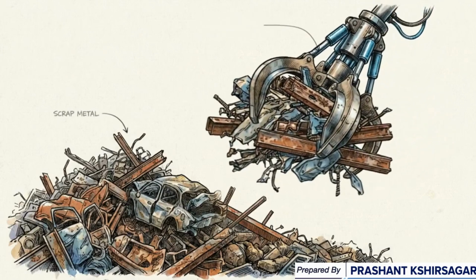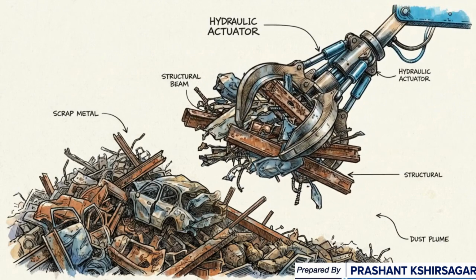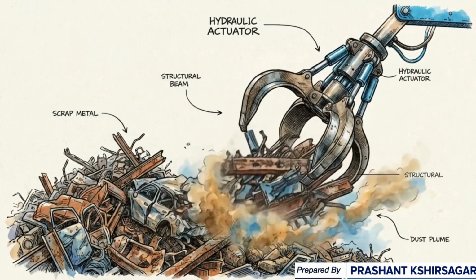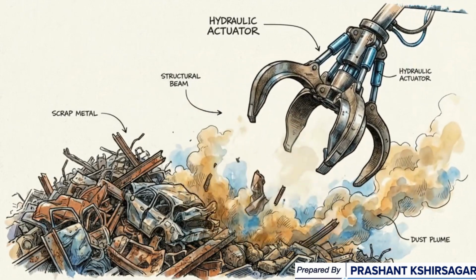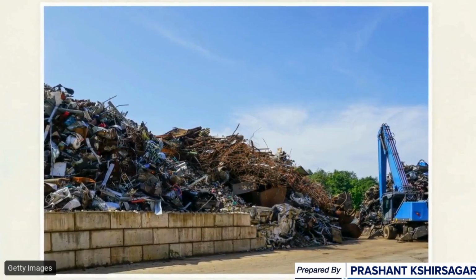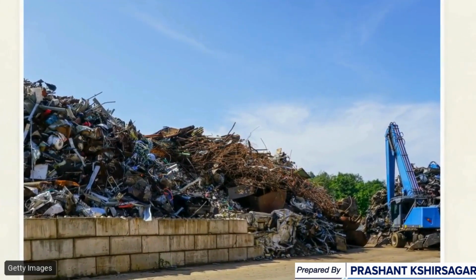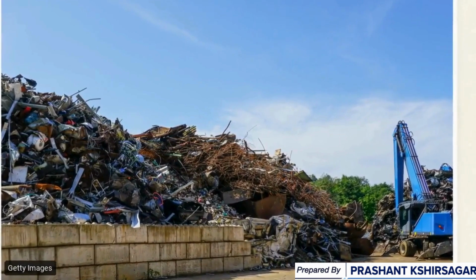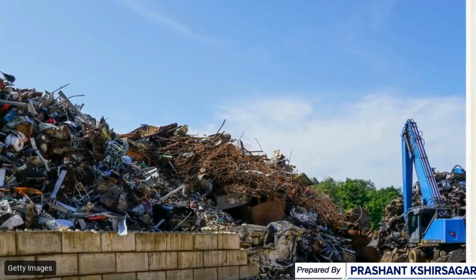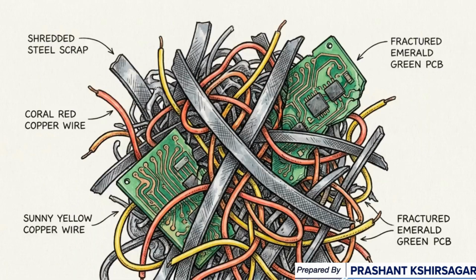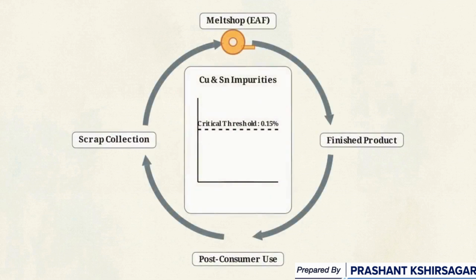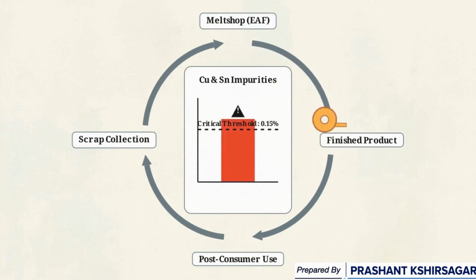The transition to electric arc furnace steelmaking demands scrap. While EAF production is growing by 4% annually, the global supply of clean prime scrap remains flat. Steelmakers are forced to rely on heavily contaminated post-consumer material. Hidden inside this recycled mix are copper and tin from automotive wiring and electronic waste. Because steel is continuously recycled, these impurities compound with every cycle, creating a physical Tramp element time bomb.